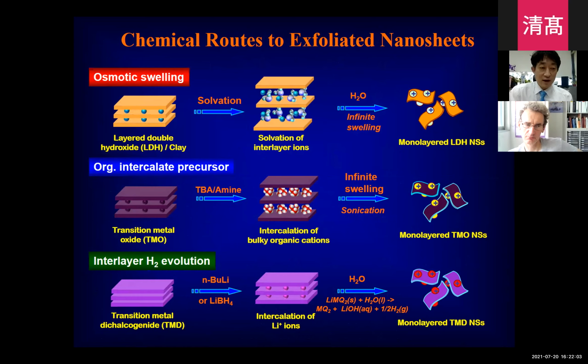In case of layered double hydroxide and clay, those materials are highly swellable. So if you soak those materials in an appropriate polar solvent, we can induce the infinite intercalation of solvent molecules. In this way we can get monolayered LDH and clay nanosheets with the assistance of a dissolution process. In case of layered transition metal oxide, there is exchange of the cationic species. So we can replace the interlayer ion with a bulky organic cation. In that way, we can minimize the interlayer interaction. Eventually, we can get the monolayered TMO nanosheet.